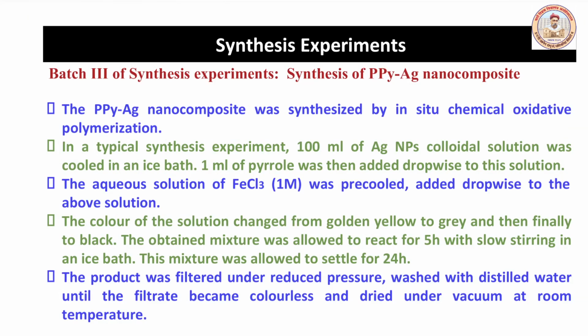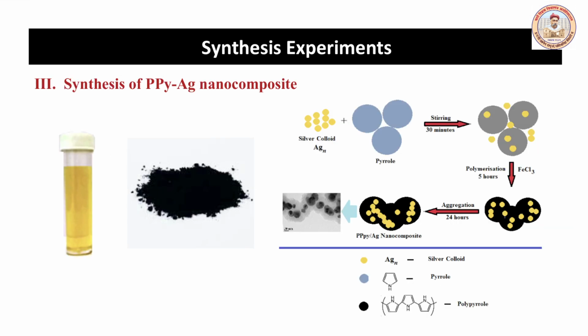The mixture was allowed to settle for 24 hours. The product was filtered under reduced pressure, washed with distilled water until the filtrate became colorless and dried under vacuum at room temperature. The figure shows the scheme. We have silver nanoparticles, then polypyrrole powder, and exactly how the synthesis of polypyrrole silver nanocomposites has taken place. Now we have completed phase 1 of experimentation.